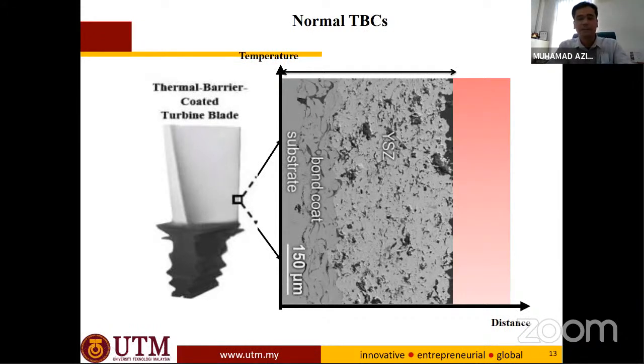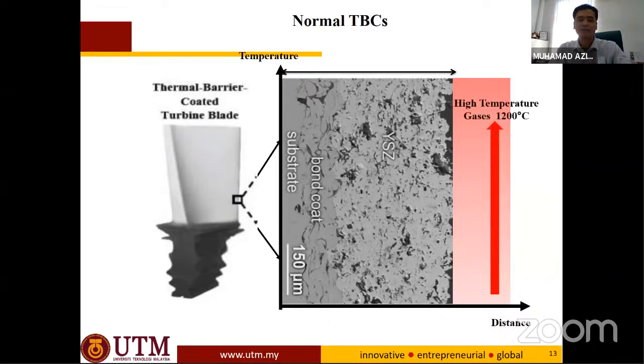Right. So if we are talking about temperature, 1200 degrees Celsius is what the coating can go to. If you're talking about the metals, for example nickel superalloy, the maximum operational temperature is around 800 to 900 degrees C. But if you have the ceramic coating, it can work up to 1200 degrees C. That's basically very simple terminology: if you have the ceramic, you can enhance the temperature stability of the component or the part.